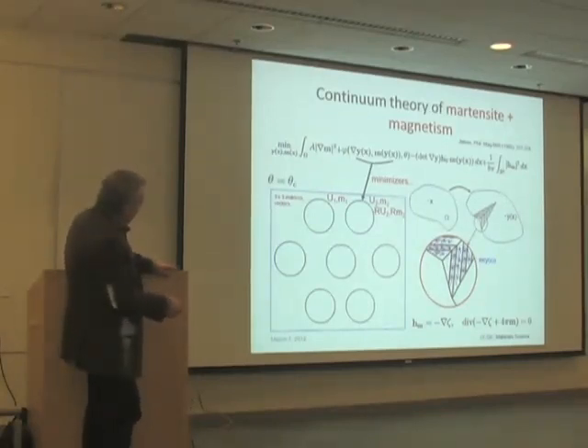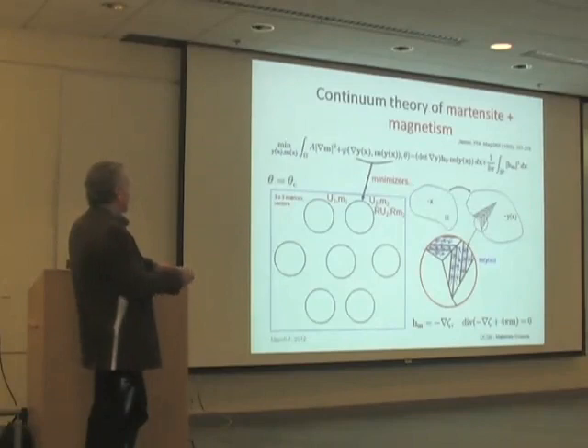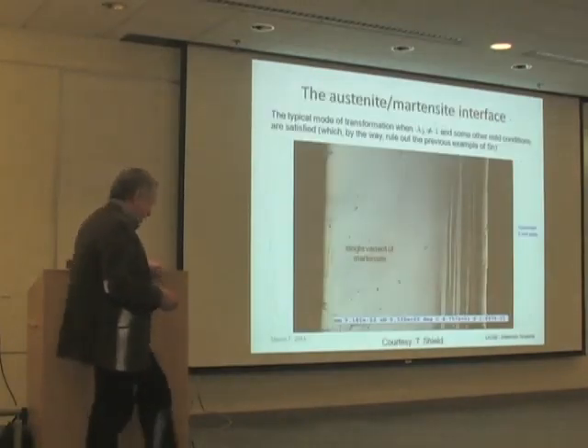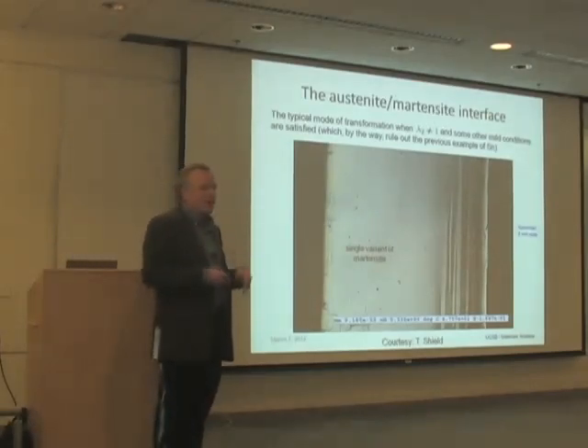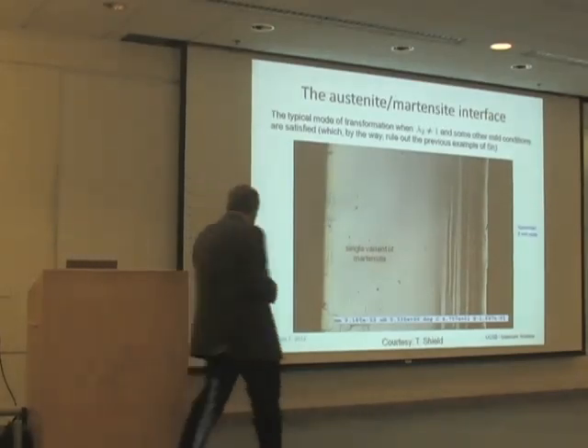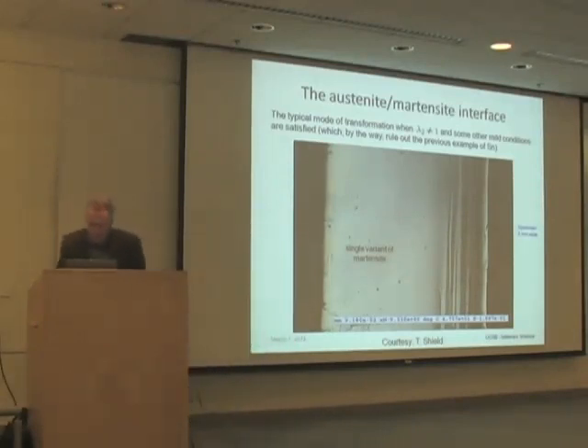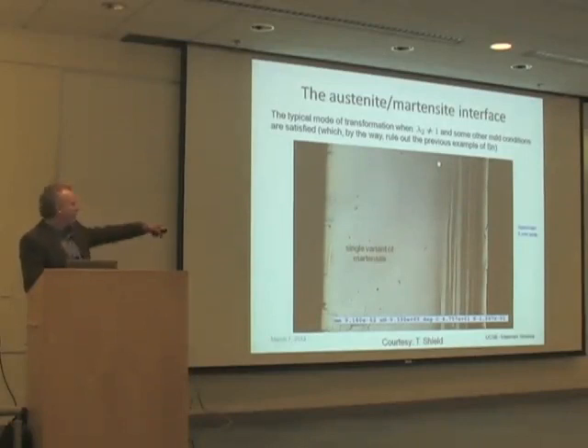And of course, when you transform, you can have shape changes because of the distortion in the phase transformation, but you also can have magnetism. And so there's magnetic domains sometimes within. This would be a very typical picture of a low energy structure predicted by this kind of theory. All right, now I want to show a picture of a martensitic phase transformation which is a bit more reversible than the last one, but it's an interesting story. So that's a single crystal, and that's a single variant of martensite.